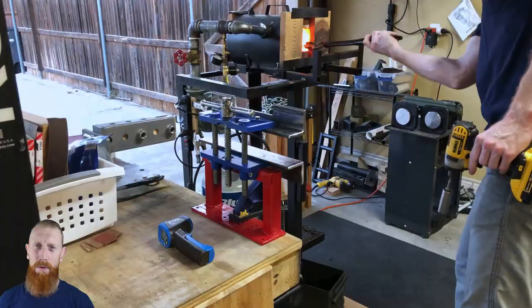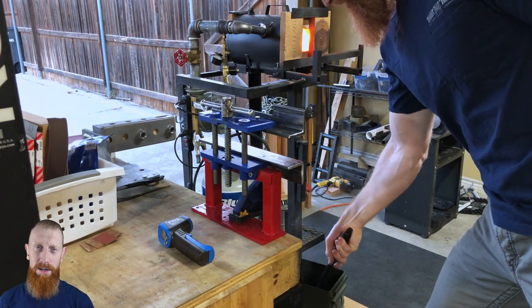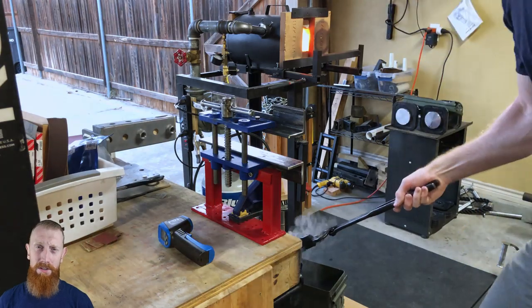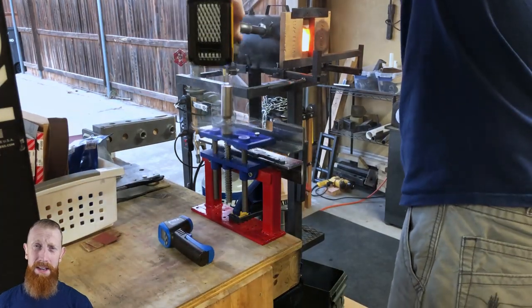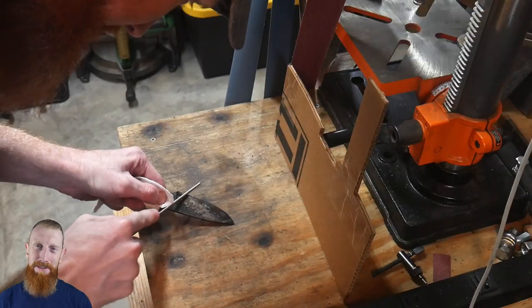This is only achievable if you can get it into the plates before it drops below 400 degrees Fahrenheit. After this, you're out of luck and you probably need to heat treat again. You will also run the risk of cracking the blade if you try to straighten it after it has dropped below 400 degrees Fahrenheit.